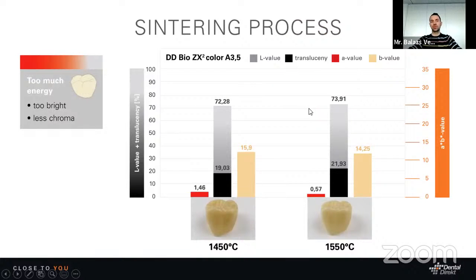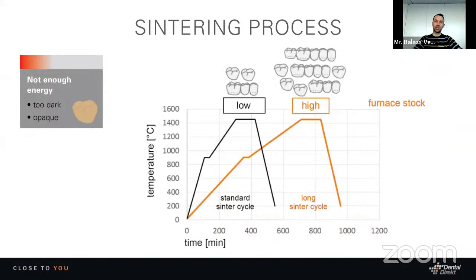A really important thing, of course, is to say a few words about the necessary processes, the sintering process. This is a really critical part, because if we need color stability and color reliability during the process, we always have to check the sintering process. If we have too much energy during sintering, our colors, our shades, could end up too bright and with less chroma. So it's really important that we pay attention to the sintering and to the proper calibration. For this reason, we always have a really nice and precise recommendation.